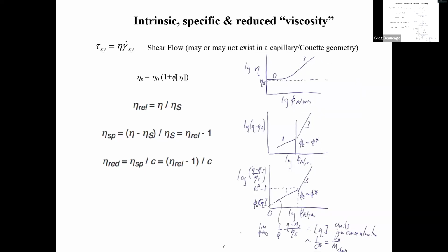So your natural thing would be to divide the solution or the colloid viscosity by the solvent. That gives you what's called a relative viscosity. Normally, that would be called the reduced, because you're reducing this by the solvent. But they call it relative because they have another reduced that somebody came up with, right? Probably Herman Mark or someone came up with these terms. So these terms are pretty confusing. You'll see them standardly plotted, so you have to kind of know. It's useful if you can remember somehow what's going on here. So I would call this reduced though, but they call it relative.